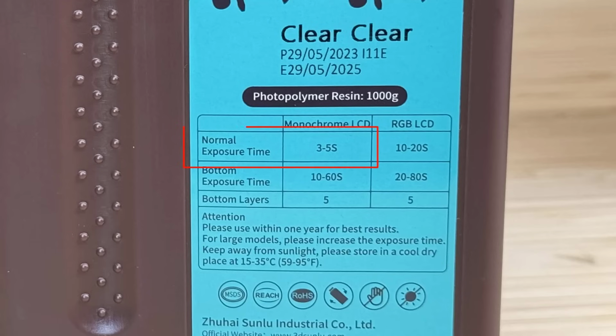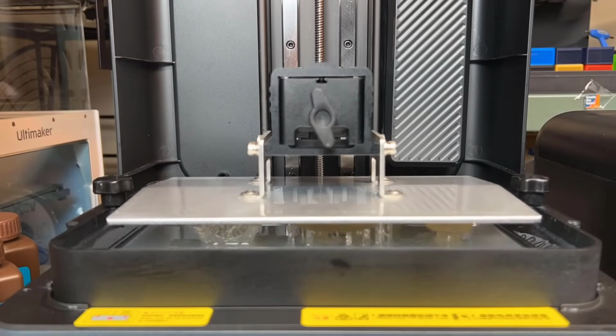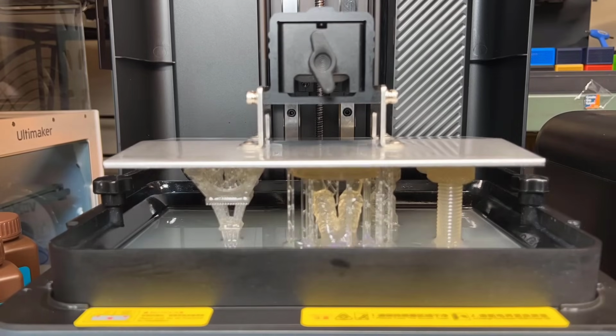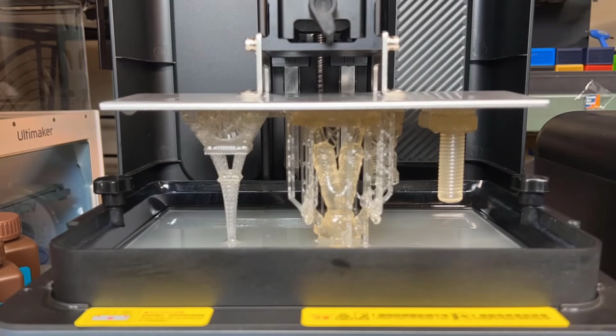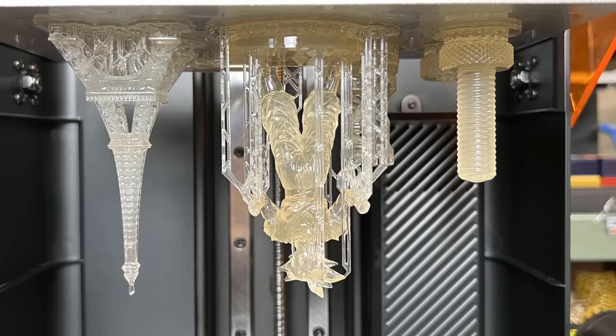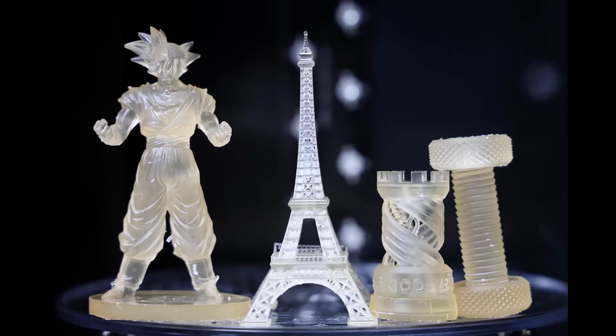It requires a slightly longer exposure time, ranging from 3 to 5 seconds per regular layer. However, I'll keep the same settings of 3 seconds for regular layers and 30 seconds for the bottom layers to see if it affects the print. The print seems to be quite successful, even with a 3-second exposure time instead of 5. However, the resin turns yellow, similar to other clear resins. The models with solid bodies are more yellow than the Eiffel Tower. I will perform a temperature resistance test later and compare with other resins.